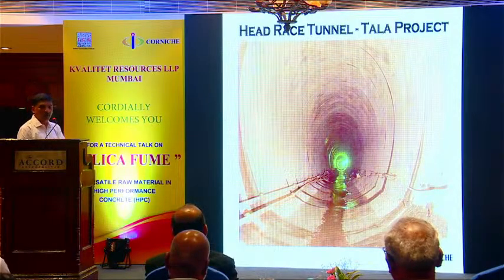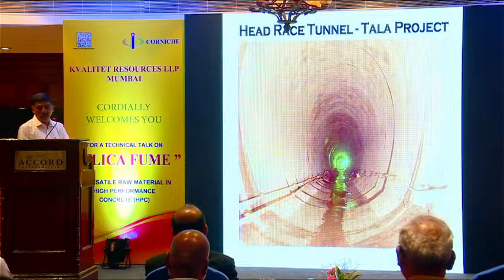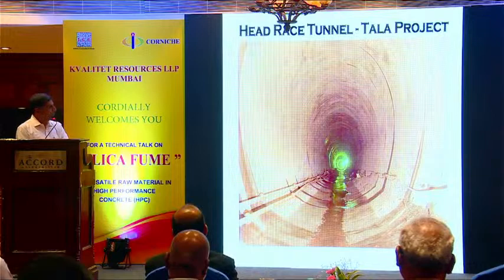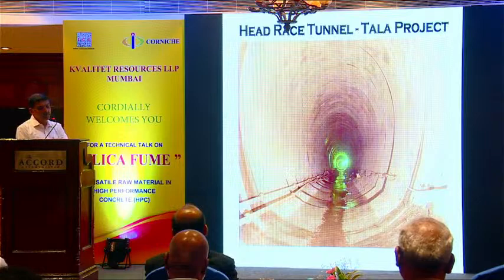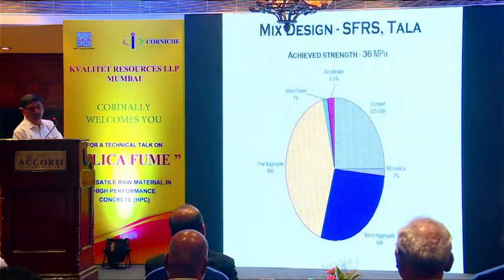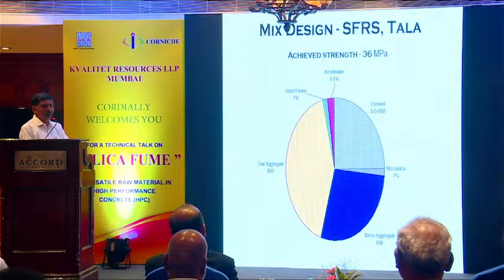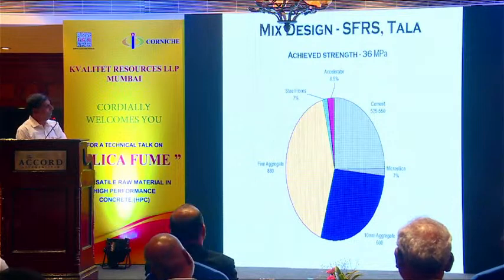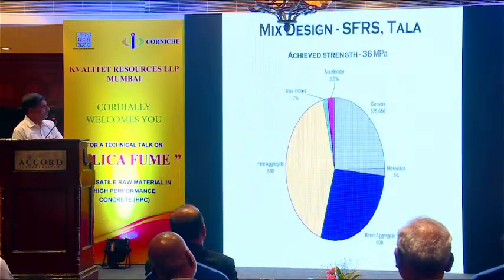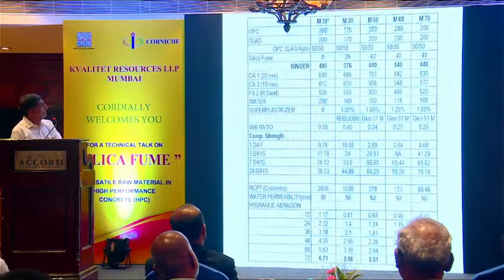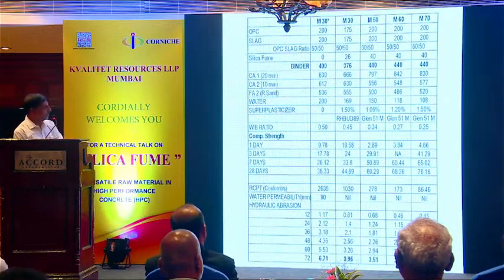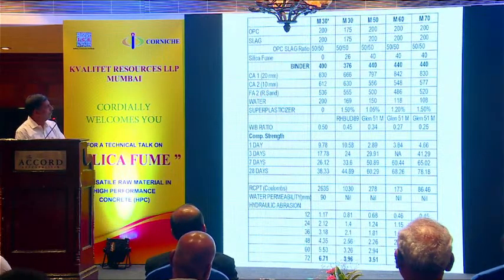The tender-specified quantity for silica fume was only 73 tons. 9-10 years later, when the project was completed, they had consumed more than 22,000 tons of silica fume. A 28.5 kilometer tunnel, the entire tunnel was shotcreted with silica fume steel fiber shotcrete, SFRS. Typically M30 SFRS. The mixes, and the testing we had done, I have just compiled all the results here.